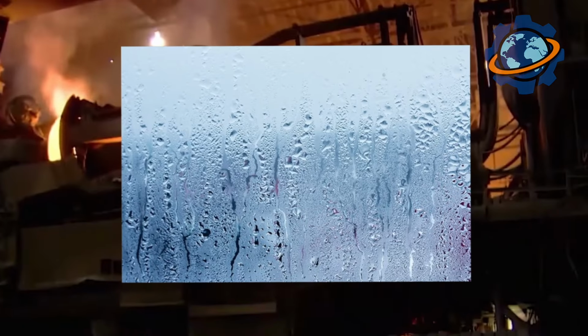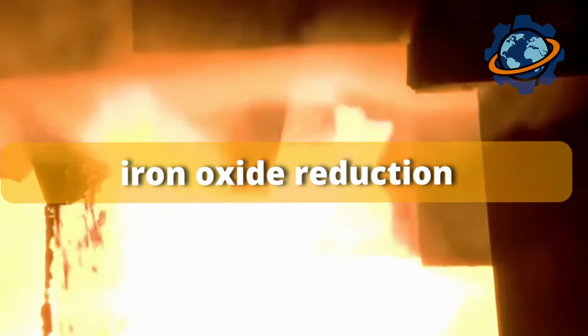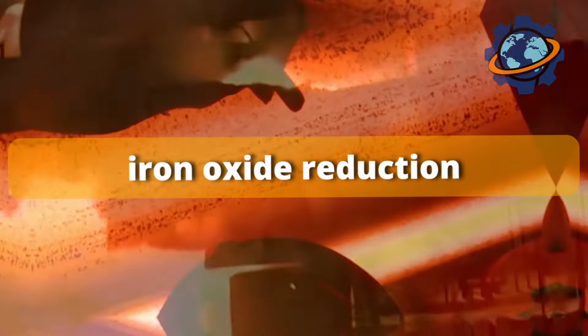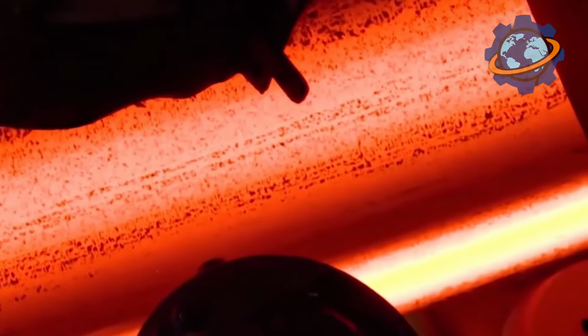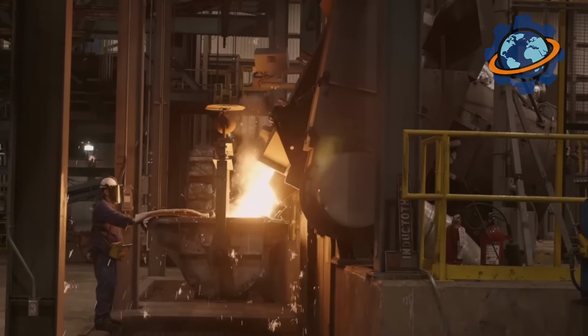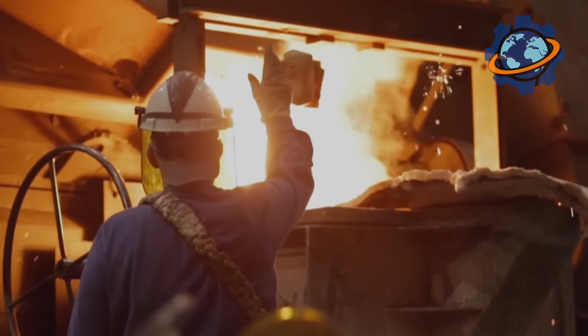Different reactions occur at different heights. First, moisture leaves the ore. Then, at 930 degrees, iron oxide reduction begins. Carbon from coke strips away oxygen. At 1800 degrees, ore becomes spongy iron. At 2700 degrees, iron melts. Drops of molten metal flow down.